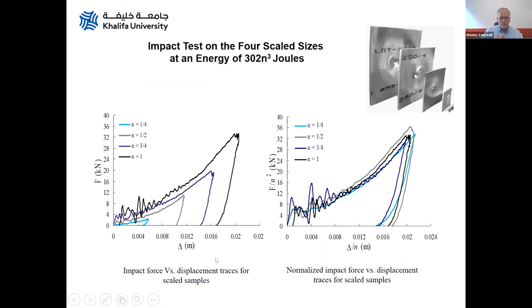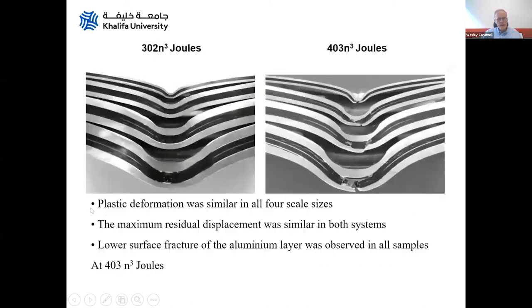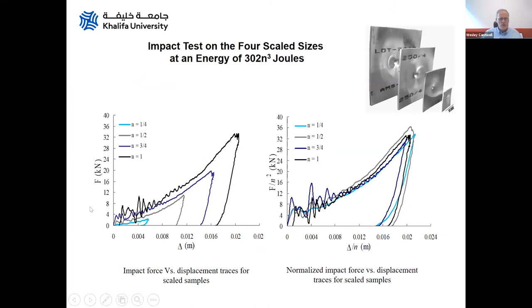So we go ahead and test them, we impact them. We take our four scale sizes and we have our four sizes of support and striker diameter, et cetera. Sorry about that. We measure our force against displacement and we've got our four different sizes of sample in there. There's our N equals quarter, the smallest one. Clearly it's a very small sample impacted by a low energy, and we get this response down here, maximum force of sort of 2 kilonewtons and a little bit more. There's our N equals half, three quarters, and our full size.